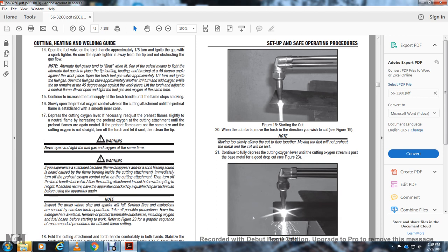17. Depress the cutting oxygen lever. If necessary, readjust the preheat flame slightly to a neutral flame. Increase the preheating oxygen with the cutting attachment so the preheating flames are again neutral. If the preheating flames are not the same size and the cutting oxygen stream is not straight, turn off the torch, let it cool, and clean the tip.